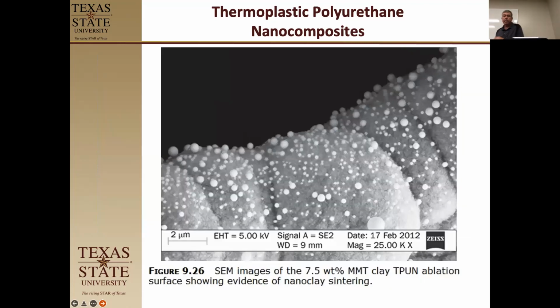All right. And then what they found when they looked at one of the systems is they zoomed in really far and they saw these little beads. What happened? Actually, it turns out that I've seen this phenomenon before when I did pyrolyzing nickel for lithium-ion batteries. And what happens is the montmorillonite is actually decomposing and melting. And when it melts, it turns into little spheres and it cools back down. Decorative spheres of molten silicate. So the heat flux was so high that it actually melted the montmorillonite. So these are little spheres of silicates.